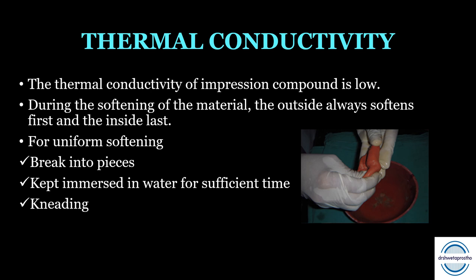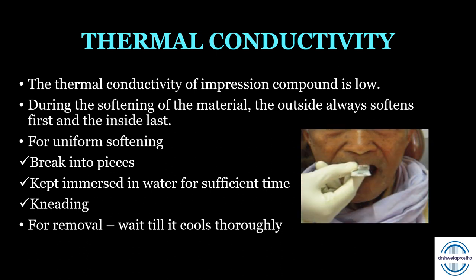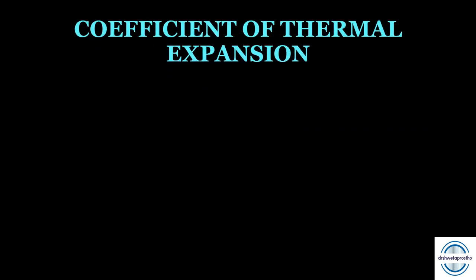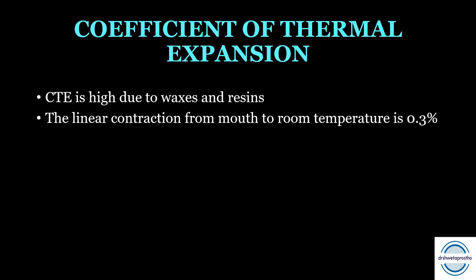Low thermal conductivity also affects the cooling rate — for removal, we must wait until the whole impression cools thoroughly, otherwise distortion will occur. The coefficient of thermal expansion of impression compound is comparatively high due to the presence of resins and waxes. Linear contraction occurs as we go from mouth temperature to room temperature — the contraction is around 0.3 percent.